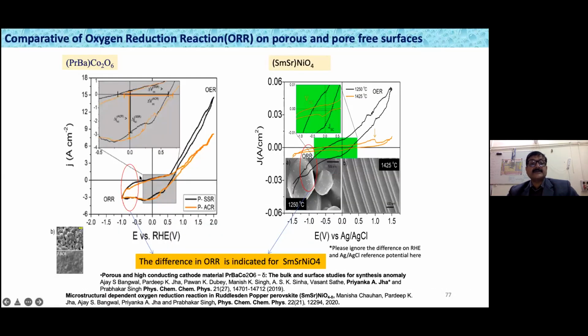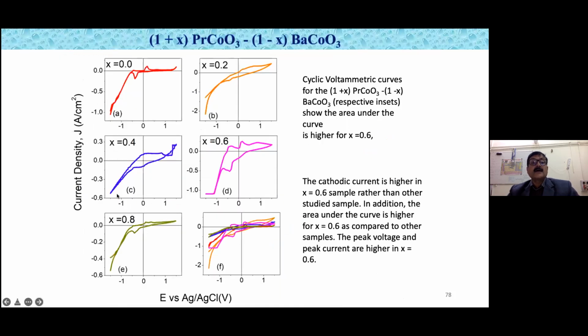The ORR, the oxygen reduction reaction, is required for the cathodic reaction, which is good. We found it for both systems, prepared through SSR and ACR, as you can see in the circle. Here we have different X values. When you increase the X value, you are increasing the Pr content and reducing the Ba content. For X equal to 0.6, we got the highest cathodic reaction, that is the ORR. You can see this area is larger than for the other values of X.